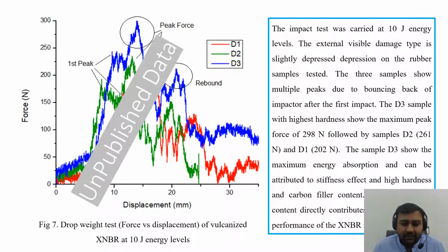So these are the results from the drop weight test, force vs displacement, of vulcanized XNBR at 10 joule energy levels. As you can see, the sample is rebounding back at different stages, and several peaks are observed. There is no damage to the samples, and just a depression is formed on the rubber. And the sample with the highest hardness shows the highest energy absorption peak.